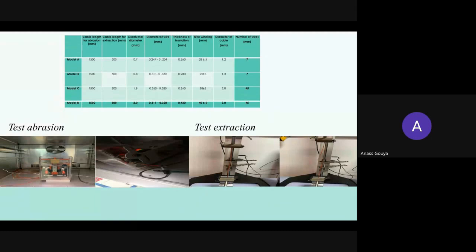Each geometrical and mechanical characteristic could have an impact. For the experiments in this study, a cable consisting of two materials was chosen. The first one is copper conductor with Young's modulus of 120 GPa and Poisson's coefficient of 0.34. The second is PVC insulation with mechanical properties of 3275 MPa for Young's modulus and Poisson's coefficient of 0.32.